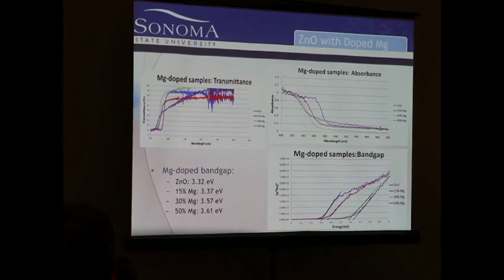And so zinc oxide tends to have a 3.33 electron volt band gap, and experimentally, this black line, which is where I calculate the band gap, indicates that our zinc oxide had 3.32 electron volts.